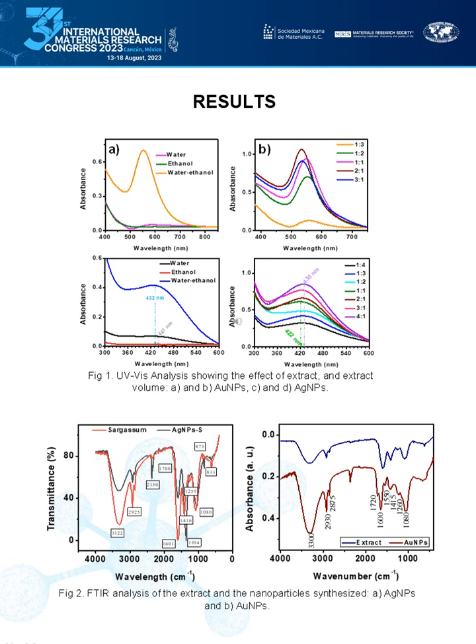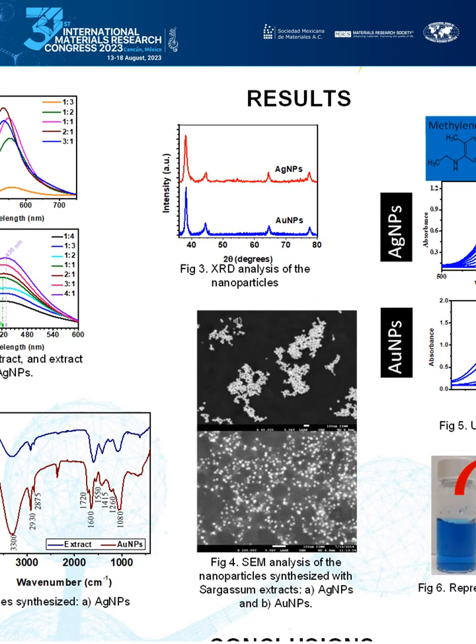The samples of the extracts and gold and silver nanoparticles were analyzed by infrared spectroscopy. The results showed changes in the signals of the bonds corresponding to the phenolic compounds, for which the reduction of silver and gold ions is attributed to this type of compounds. On the other hand, the crystalline nature of the samples was corroborated by X-ray diffraction, where the presence of silver and gold was evaluated as unique phases, but with a face-centered cubic structure.